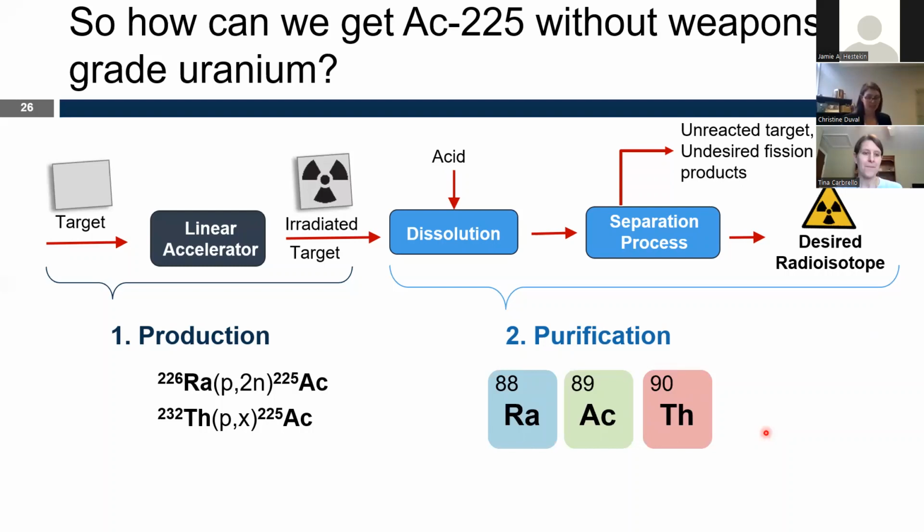that result from nuclear reactions is that if you're bombarding with protons or even small nuclei, usually the reactions that are accessible just by probability are a lot of the neighbors on the periodic table. So usually your separations are 3 in a row. And if you're doing that for lanthanides, it becomes tricky because lanthanides are very chemically similar. If we're doing it across some of the actinides and then radium, we have a little bit of benefit: they have different oxidation states. But all of those things really get factored into designing these specialty separation materials.